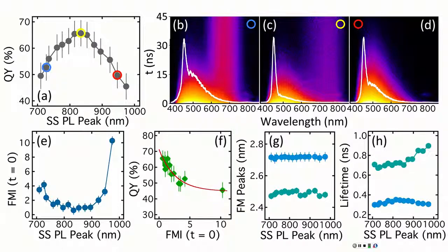Yeah. But it is a defect. And because they are very high energy, localized, the dependence on K would be very shallow, almost no dependence, right? Would be kind of constant. Your parabola will not really be a parabola, it's a very shallow one. Their position might be kind of low in energy compared to the gamma point, but not necessarily to the other point.